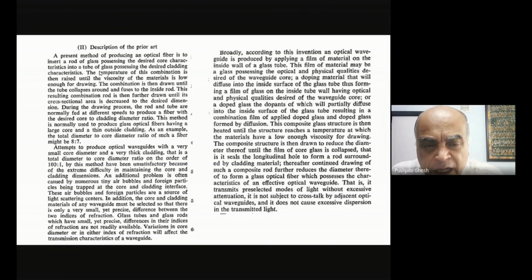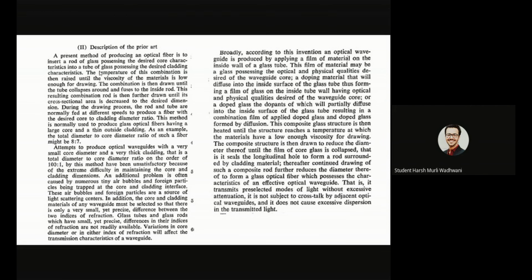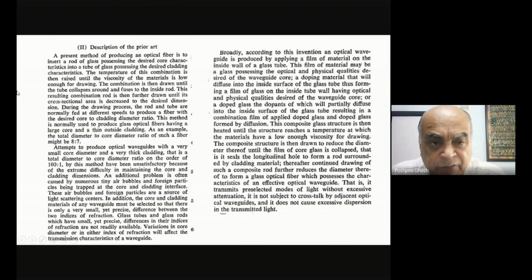So you're just inserting one glass into a tube. Out of this, which one will have the higher refractive index? The core, the rod. Yes, the core will have the higher refractive index. So obviously, whatever you are inserting must have that kind of property. The temperature of this combination is then raised until the viscosity of the materials is low enough for drawing. So it becomes softened, the glass, and then you can draw just like glass blowers do. That's effectively how they make different types of shapes and sizes of glass objects.